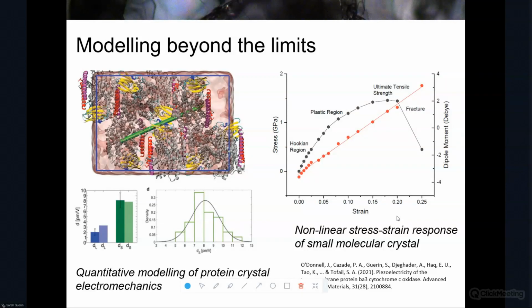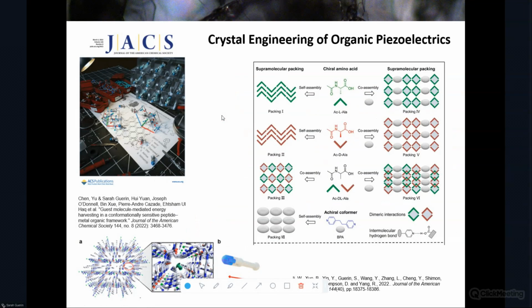And because we know that, again, you get more and more charge buildup as you apply more and more force, we can also track how the dipole moment develops in our crystal with increasing force over various regions. So just 2 different cool things that we've developed for if you have anything from an amino acid crystal all the way up to a protein crystal, which is also solvated, we can get very high accuracy for piezoelectric predictions.